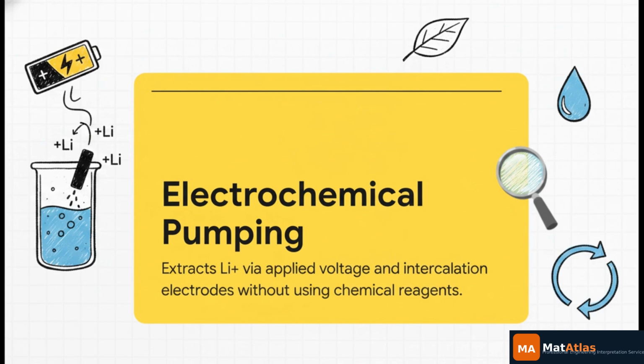Electrochemical ion pumping acts like a battery in reverse. Instead of dumping vast amounts of strong acids or toxic solvents to chemically force impurities out of a solution, we use applied electromotive force. We place a highly selective electrode into the brine, apply a specific voltage, and that electrode acts like a highly tuned sponge, absorbing only the lithium ions.